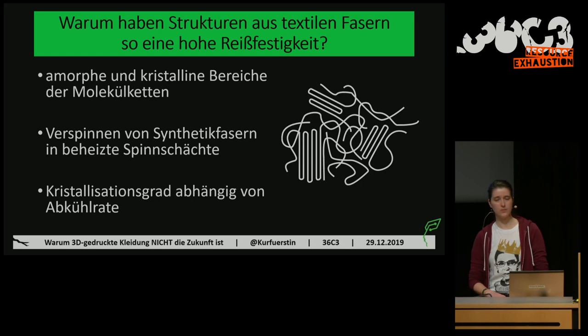So these spinning machines are heated to cause the cooling to be as slow as possible, to get a degree of crystallization that is as high as possible, and hence a tensile strength that is as high as possible. We do not have this possibility with 3D printing. We can use a heated print bed, but that only influences the first one or two layers maybe, and nothing after that.